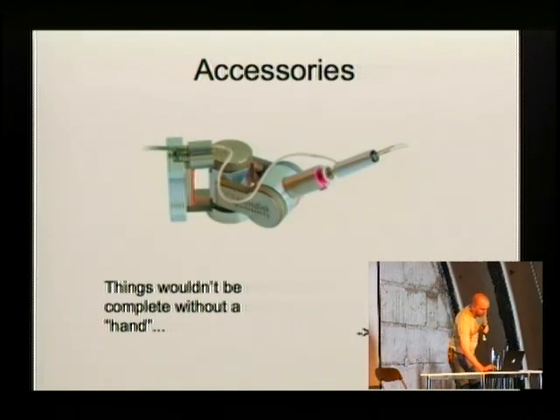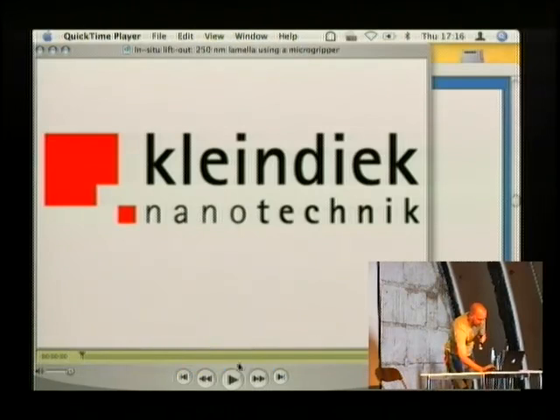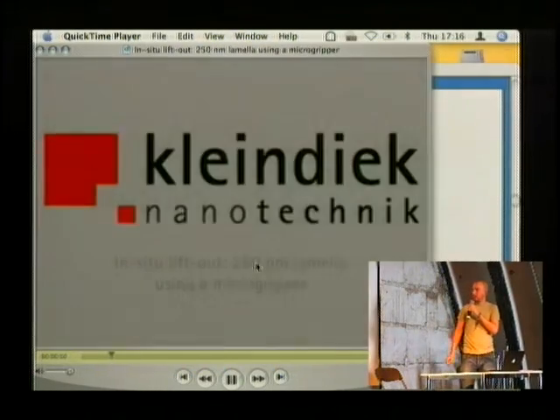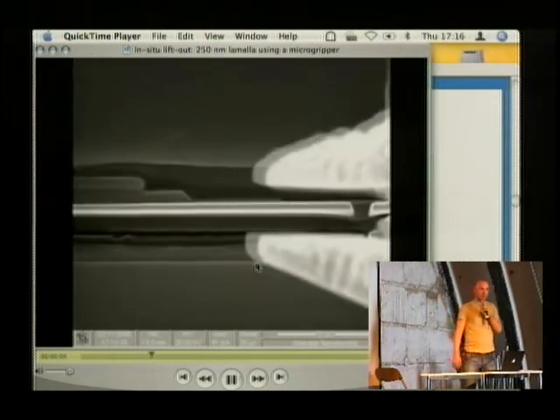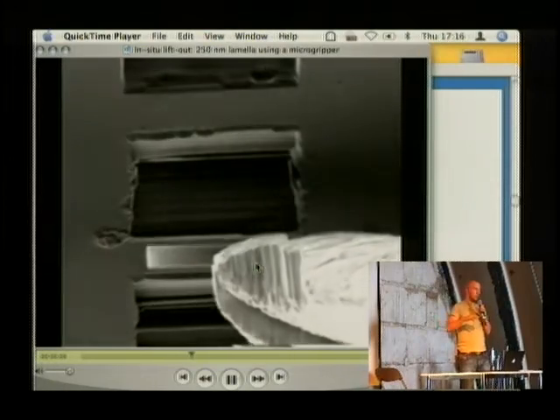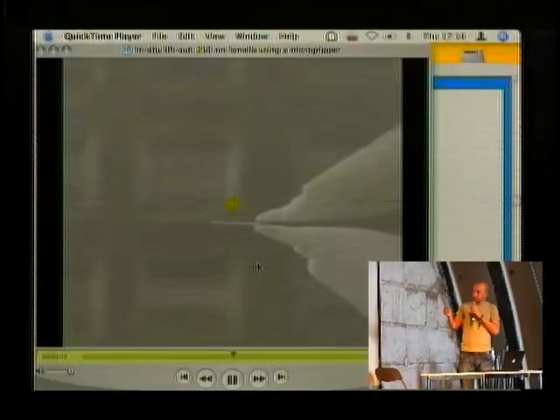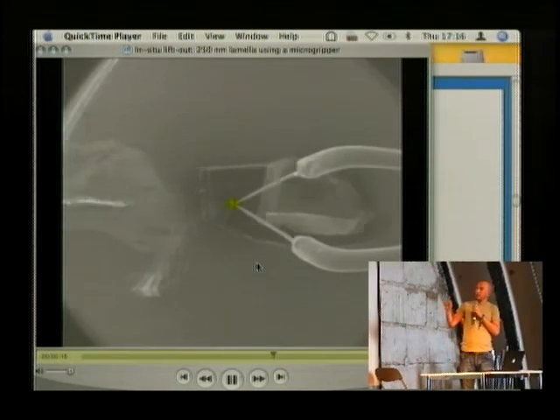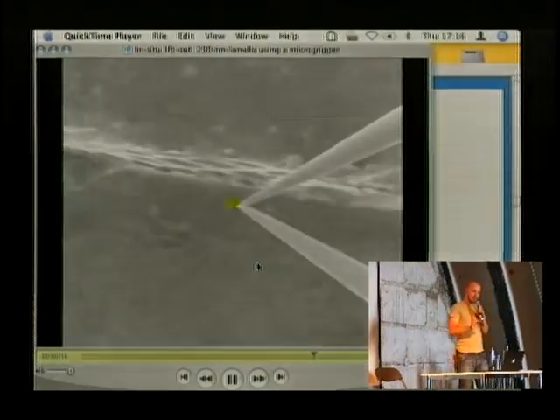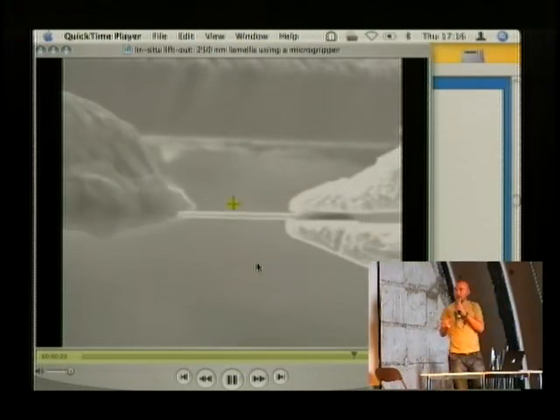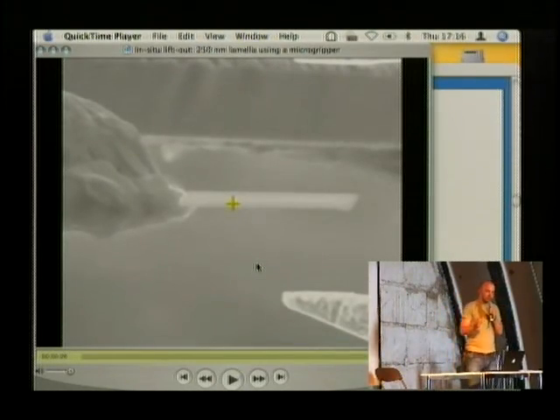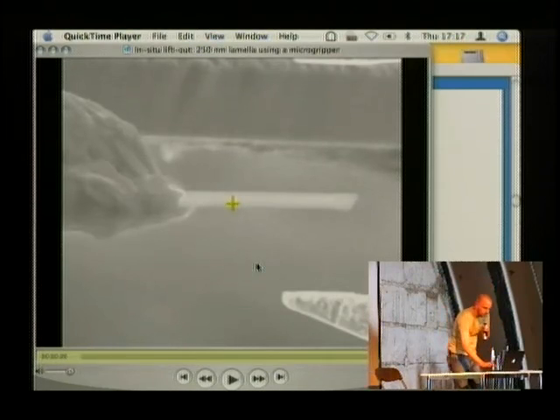Things wouldn't be complete without the hand. So I have this little video that maybe works. Typically in these systems you also have some sort of micro or nano manipulator. Here's a demonstration by Kleindiek. They built these grippers that can pick up nanometer-sized objects. You can transport them within the FIB. You can use the focused ion beam to cut off pieces of interest, take the gripper, move them around, and weld them to other surfaces. So this is a pretty powerful tool.